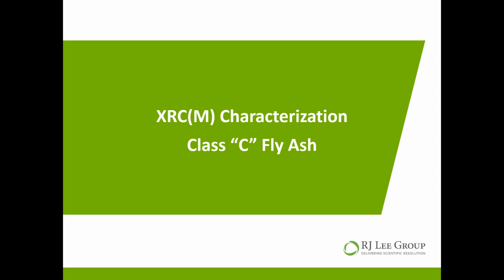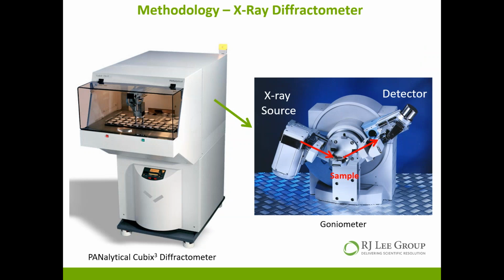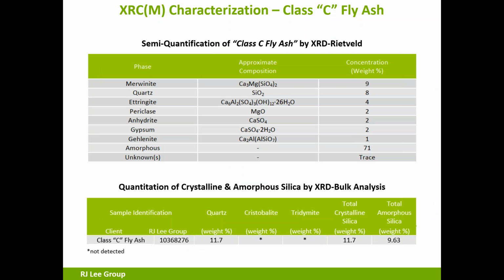So let's jump into some fly ash, see what we did. Class C. To start the characterization, we're going to kick it off with X-ray, and we're going to use that X-ray to determine what the ingredients are using a method called XRD Rietveld. And in the case of one of the Class Cs that we've analyzed, these were the ingredient categories. So what's happened here, and I realize that for some this may be confusing: how can you have something that's been combusted and all of a sudden it's got mineral species? That is how this works.